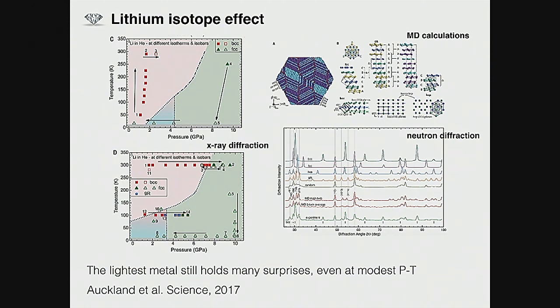They use, of course, experimentally, this is very difficult. You want to have as many different observations as you can. And in most of these studies, you also need first principles calculations to model and predict your structures. So they did a comparison of total energies, but they also did molecular dynamic simulations, and they actually showed that the phase that was supposed to be 9R, the ground state phase of lithium, is actually most likely a martensitic-like crystal structure that they found with molecular dynamic simulations, and then they used it to reinterpret neutron diffraction data, and they claim that's a better fit.